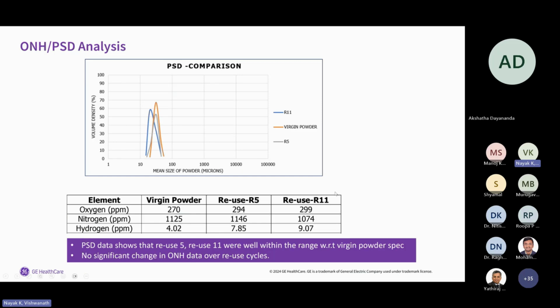We also do the ONH and PSD analysis. You can see the oxygen content slightly increased, but nitrogen was almost similar, and hydrogen increased a bit, but it is well within the specification range. We saw the different conditions, and we plotted that against the virgin powder here.